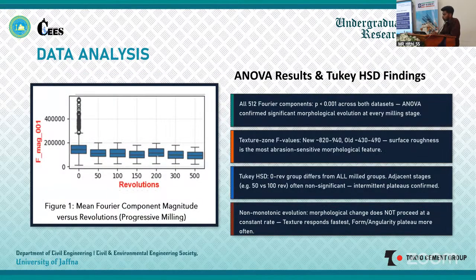ANOVA result: all Fourier components change significantly throughout the milling process. The texture zone recorded the highest F values, indicating that surface roughness is the most sensitive characteristic affected by abrasion. The Tukey HSD also showed that adjacent milling stages such as 50 to 100 revolutions were often not significantly different. This indicates that the morphological evolution occurs through gradual stages rather than changes at a constant rate. Let's move to the F value separability.